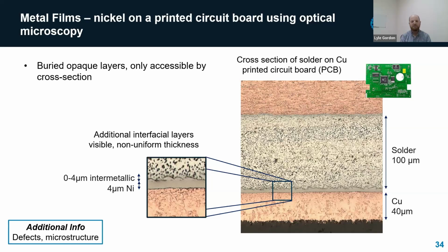And once you're preparing these, you can get insight into other aspects of your material. For example, if there's other defects or heterogeneity, or even the microstructure of the metals that your sample is made out of can also be exposed. And this applies not only to metals, but really any kind of material that you could polish or microtome, and you can see the difference. And if your films get into maybe the hundreds of nanometers range, then you could, instead of using an optical microscope like we did here, go into a scanning electron microscope. And that gives you different contrast as well. So certain materials might be easier to see the differences.